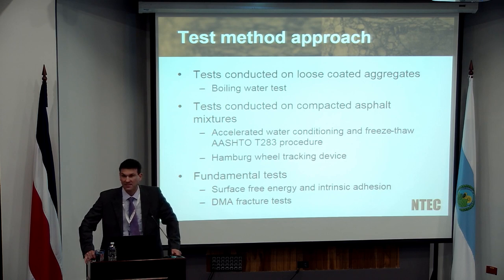We know that there are lots of tests in terms of compaction of the asphalt mixtures in terms of doing bulk testing. So AASHTO T283 is used universally throughout the world. And so in the UK, we would tend to use a derivative of the AASHTO T283, which is the US system. But of course, there are other ways of doing it. Hamburg wheel tracking, immersion wheel tracking, where we're not only combining the effects of moisture damage by having the environment in a water bath, but we're also combining that with the actual traffic loading. So we know that there are tests available.